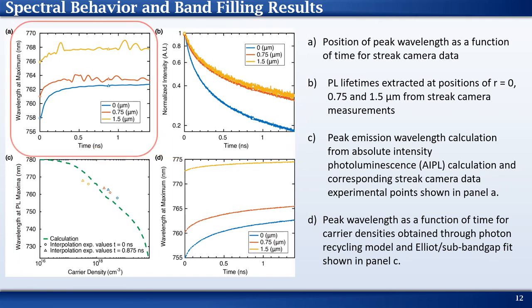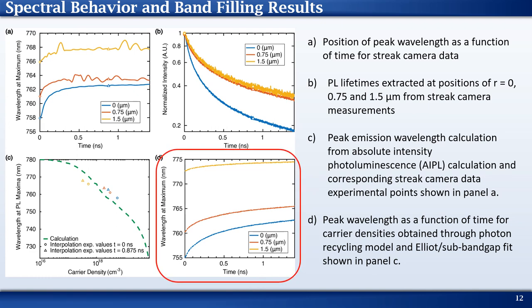Panel A shows the peak wavelength of the spectrum as a function of time. Panel B exhibits the corresponding space-integrated lifetimes at each position. The good overlap between the experimental data and the model indicates bandfilling is an important factor in the spectral shift. Lastly, in panel D we use the bandfilling results to convert photon recycling simulation densities to wavelengths. The trends in these curves match well with the data presented in panel A. This provides further evidence that bandfilling is a primary contributor to the spectral shift.